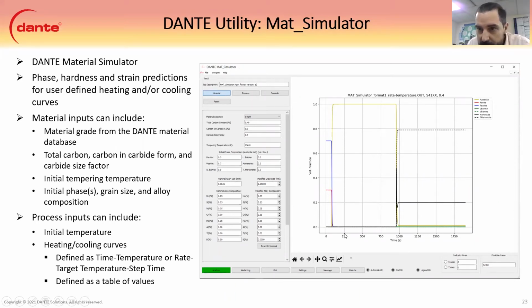From here, we see, don't have the temperature on it, but we do have a process of 4140 here. And we can see the yellow line here starts, this is the austenite, so we have a heat up. We have initial phases of ferrite and pearlite, which is the blue and the red line. They drop down to 0 as the austenite is formed. And then there's a quench here, and you can see when the quench starts, we have a martensite transformation and a tempered martensite transformation happening at the same time. And when it finishes off at the end of the process, it looks like it's maybe about 1% retained austenite, and the rest is martensite and tempered martensite. Just trying to read the graph.